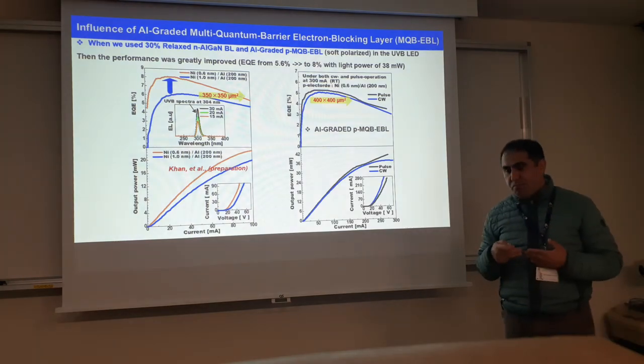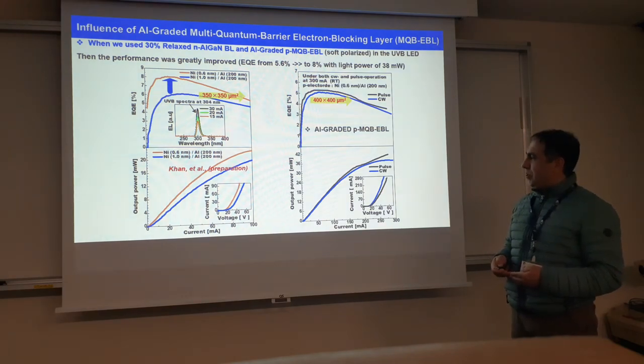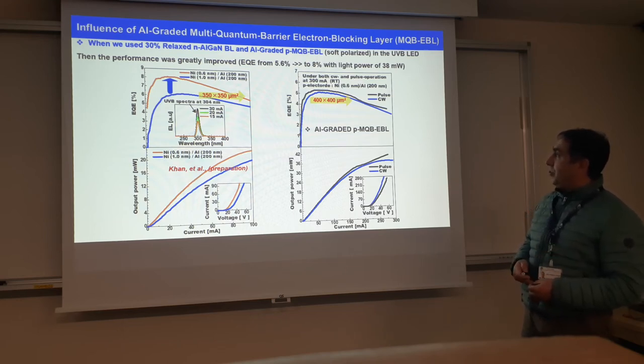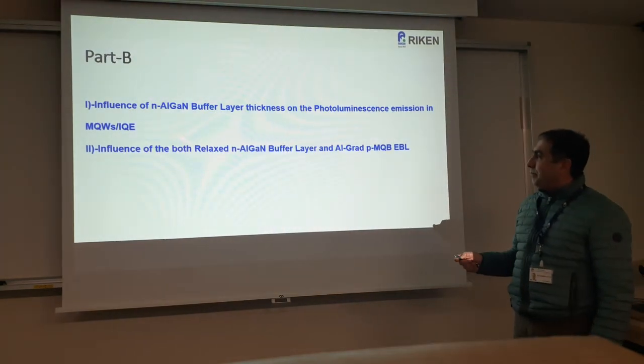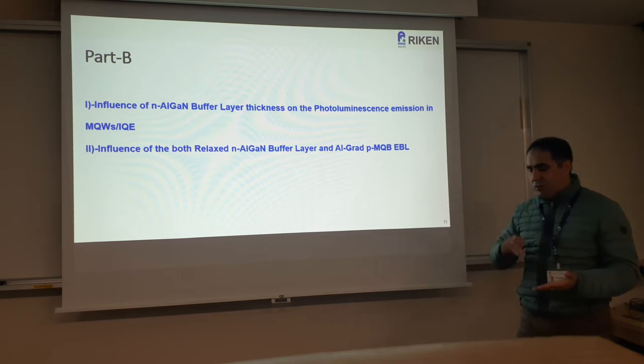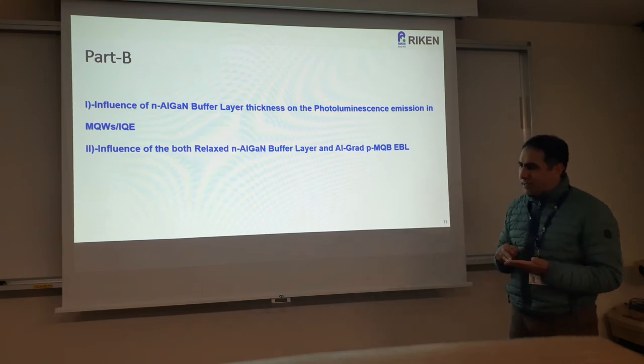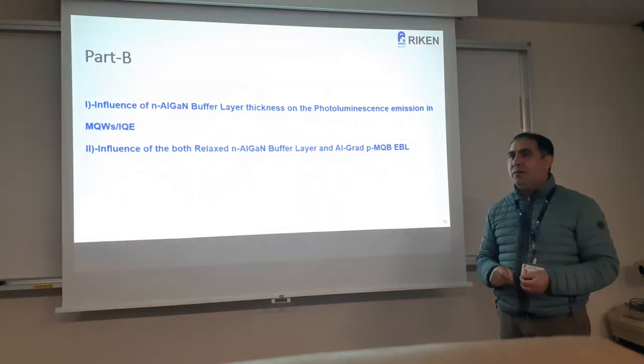We try to improve the performance further to be used for many challenging applications, like to kill the coronavirus, or for other medical applications like curing cancer. Previously we used a very thin N-AlGaN buffer layer of 1.7 micrometers. In this case, we used a thicker 4-micron buffer layer.